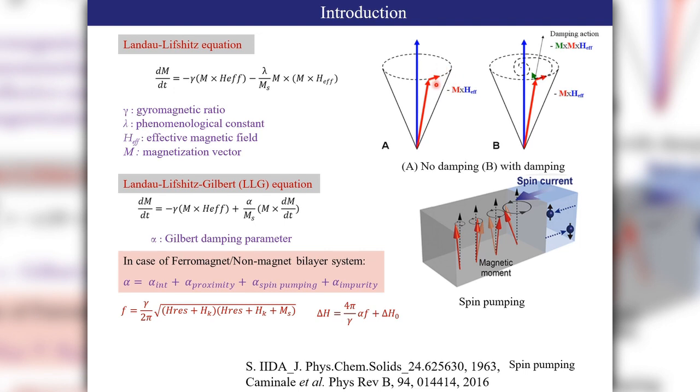But we know the spins are connected to the lattice interaction and various other factors, so finally energy will be dissipated. This damping constant is connected via intrinsic contributions, spin pumping, and impurities, and overall is found using these two equations when plotted for the ferromagnetic resonance of f versus H resonance, and then delta H versus f. Then fitting parameters are used to extract the energy factors and damping values. As spin pumping enhances the damping, finding the right spin pumping voltage is also a major task.